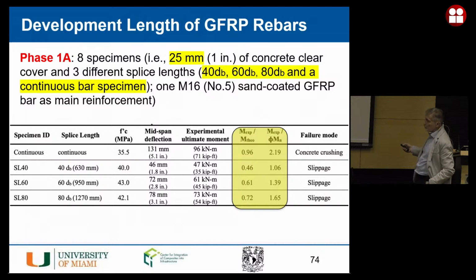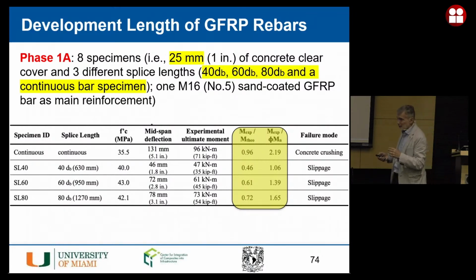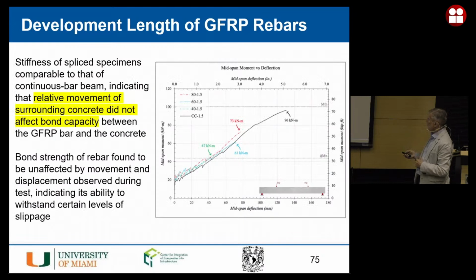But once you put the phi in front of your Mn, if you think in terms of design, if you have a continuous one, you are at 2.2 times your design need. And even with 40 diameters, which is 1/3 of what the code requires, you meet the need. I'm not saying that this is what we should be doing, but you can see the effect. And the failure is really for slippage, rather than anything else. There is very little cracking due to the presence of the bars.